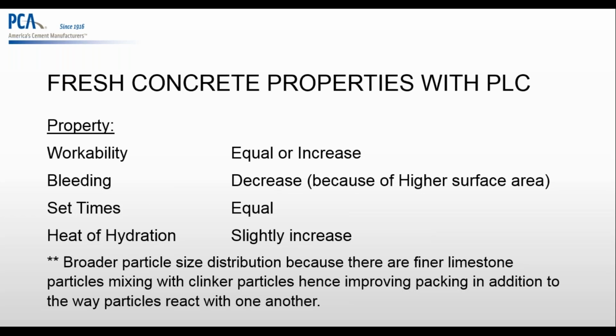So as far as properties, the workability is pretty much the same. The bleeding in your concrete should decrease, and that is because of the higher surface area. Like I said, there's more fine particles that will find the voids where the water wants to percolate or go up to the surface, and those fine particles will reduce the bleeding. The set times are pretty much equal, and the heat of hydration slightly increases depending on the reactivity of the clinker.